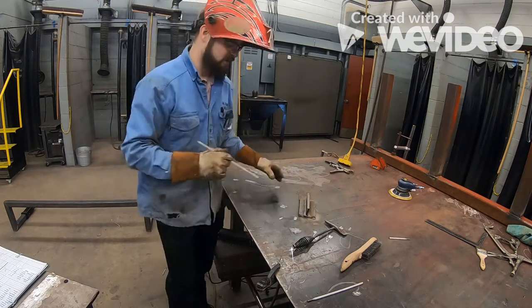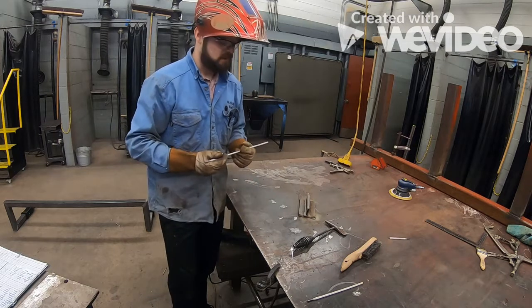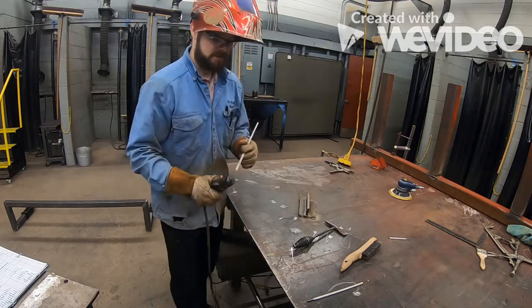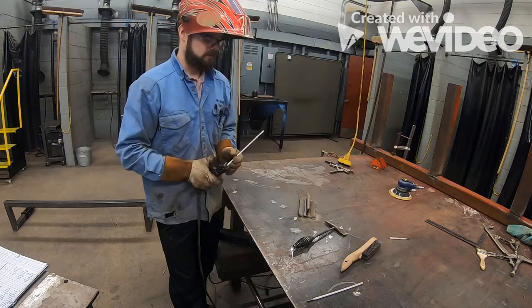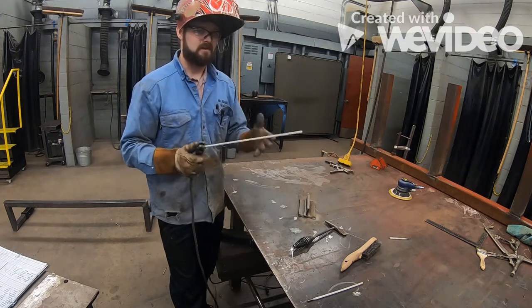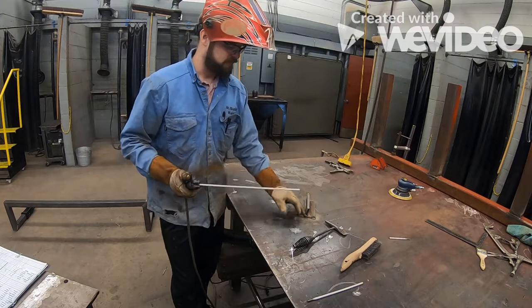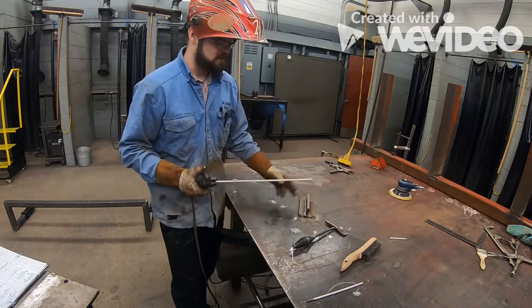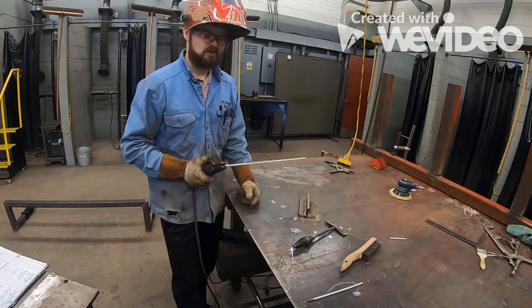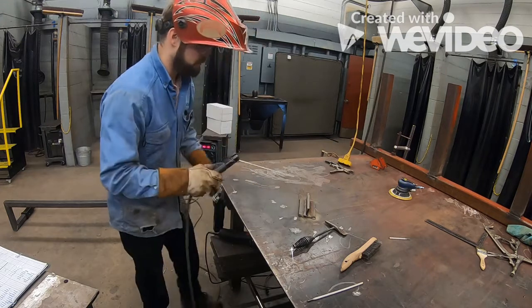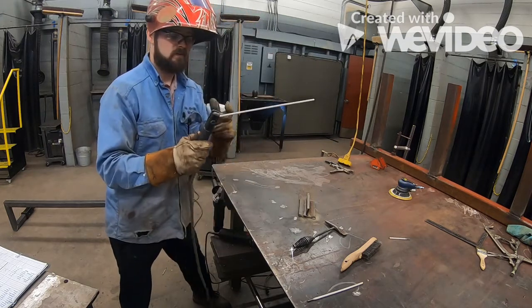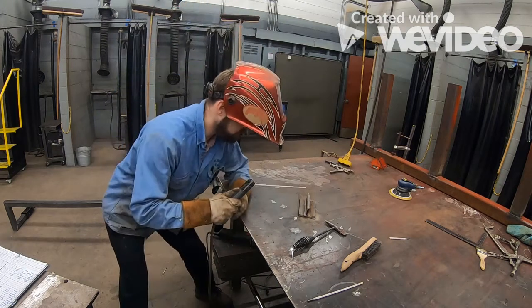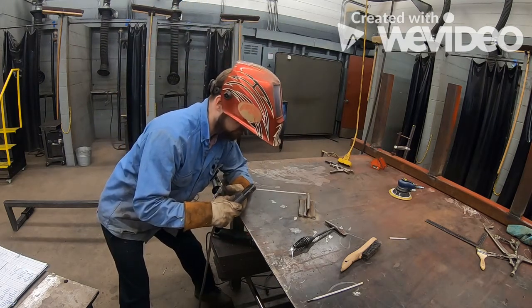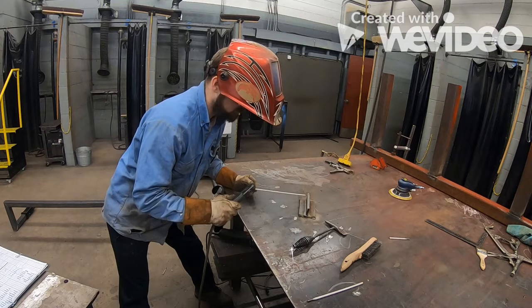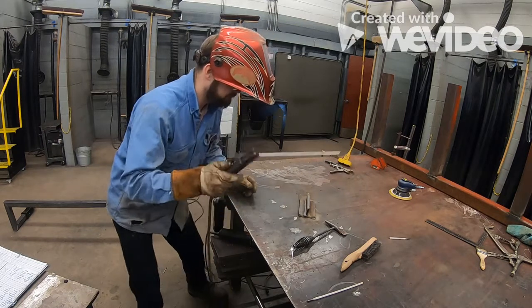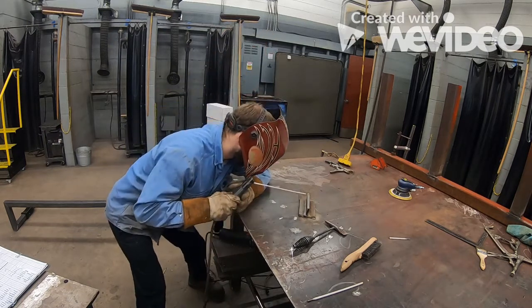I'm still welding at 140 amps, which is a little bit hot. You guys can take that down and be at like 115, 120, somewhere around that range. But 140 is pretty comfortable for me, and this metal is thick enough to where it'll take that heat. So now I moved it in the slot in here to make it much easier when I start welding. See how we have our natural almost 70-degree angle? And then fire up.